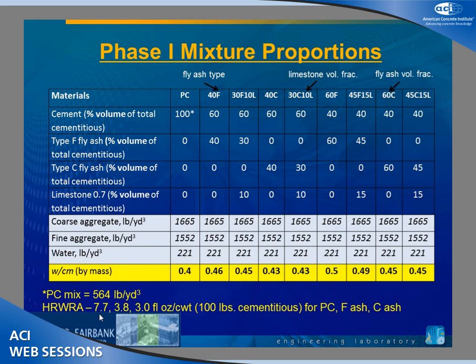And you can see, indeed, we were able to reduce from 7.7 to either 3.8 or 3 as we went from the Portland cement to the 2 fly ash systems. We had the same amount of water in each mix. Please note once again the constant volumetric proportions, which of course means if we want to report it, our water cementitious materials ratios by mass are not constant. They are different, but we felt it was much more important to keep the same water content.